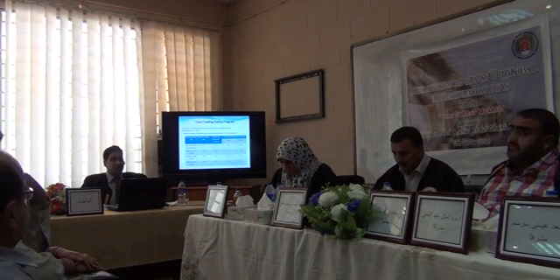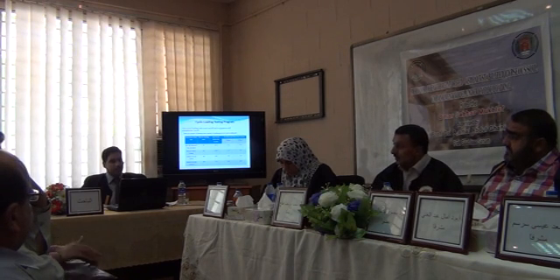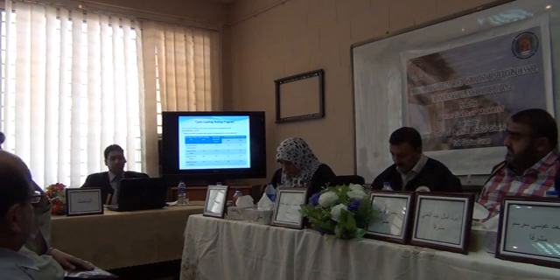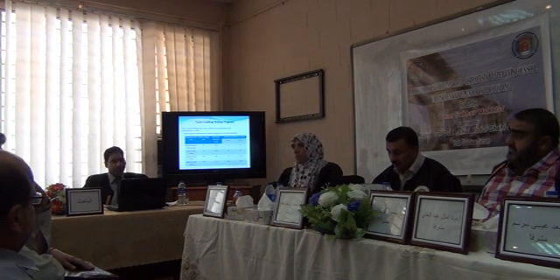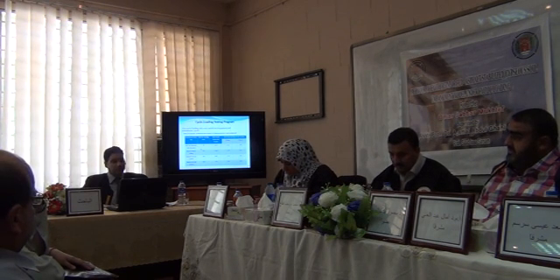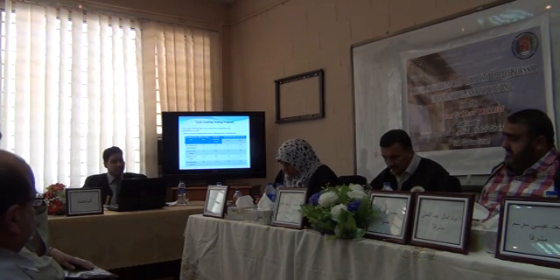Cyclic loading test program: four cyclic loading tests were carried out on the gypseous soil embankment model. This table shows deflection versus number of loading cycles. Total vertical displacement and horizontal displacement on first and third layers: pure soil subjected to water absorption — 47 loading cycles; pure soil without soaking — 165 loading cycles; stabilized soil with cutback — 436 loading cycles; stabilized soil with emulsion — 915 loading cycles.